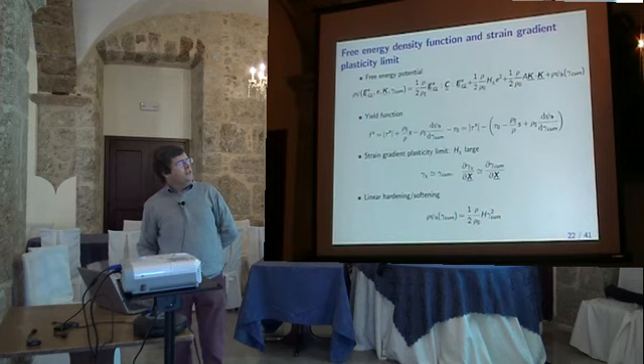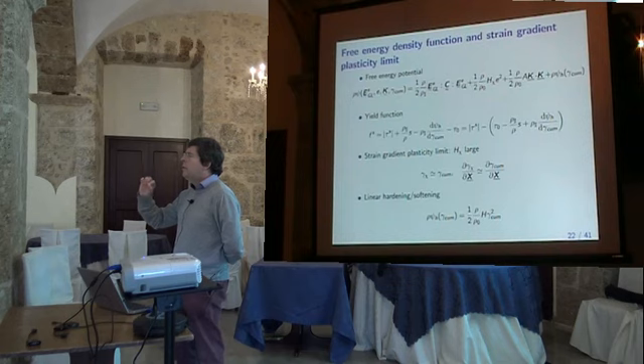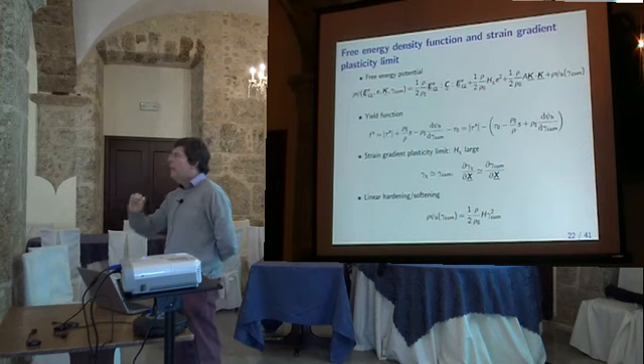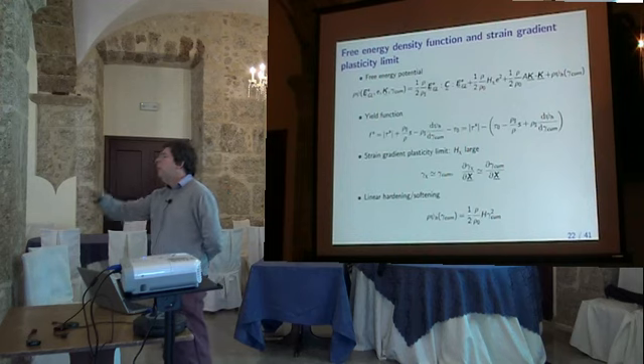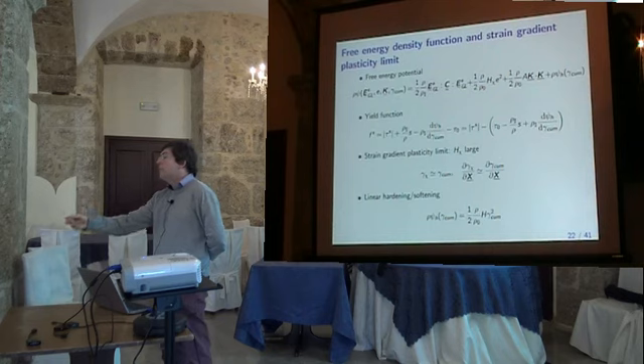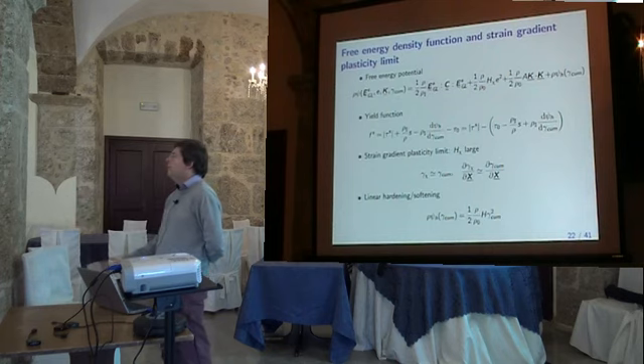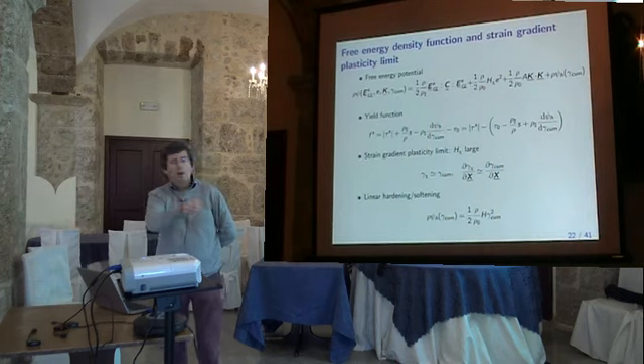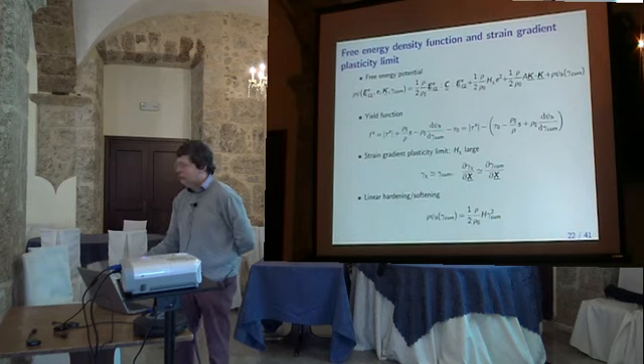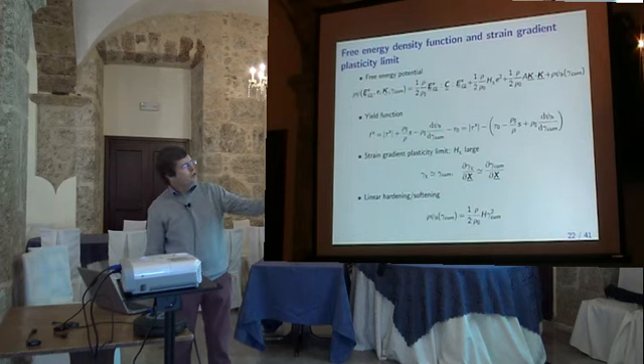Okay, it is interesting also to look at the strain gradient limit, where the penalty is so high that there is no difference between the microslip and the slip amount, simply. And then the gradient of microslip is nothing but the gradient of slip. This is a strain gradient plasticity model. And this is easier for the analytical solution, in fact. Okay, although I will show you both.